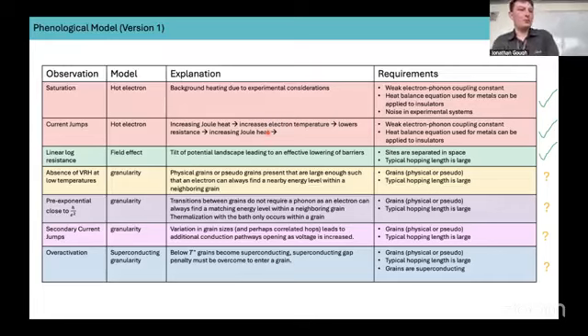So just to take a quick pause here. So far, we've observed this low temperature activated regime in disordered indium antimonide. We explain our effects in the context of hot electrons and also this field effect model. Our main assumptions are that the electron-phonon coupling is very weak, and also that we have this very large typical hopping length. We also assume noise in experimental systems to explain the saturation, but that's fairly justified. There's no ideal experimental systems.